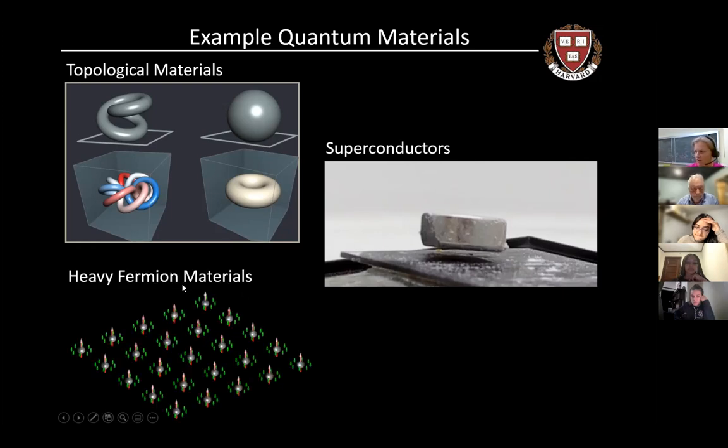And another kind of quantum material is a so-called heavy fermion material. In this case, typically the atoms have some kind of unpaired f electrons, some kind of net spin at each atom, and then the conduction electrons, the electrons that are traveling waves through the crystal, end up partially canceling the spin around each of these atoms. This causes a change of the interaction of the traveling wave electrons with the local spins, and a change in the band structure that I'm going to come back to later in this talk.